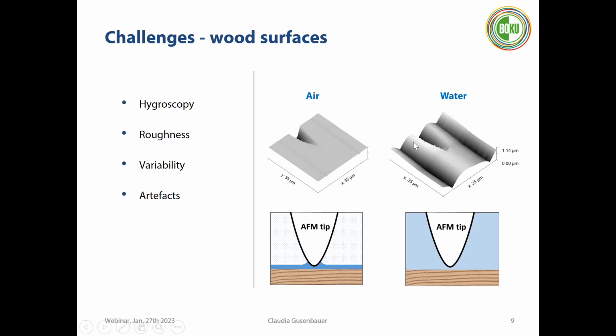And you can see on this AFM image in water, we can see the wood swelling. And this is very tricky for us because wood is not swelling in one direction the same. We have a lot of direction-dependent swelling, and we really have to follow precisely the movement when our wood sample is scanned.